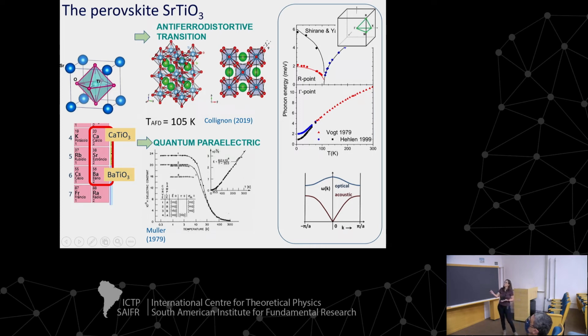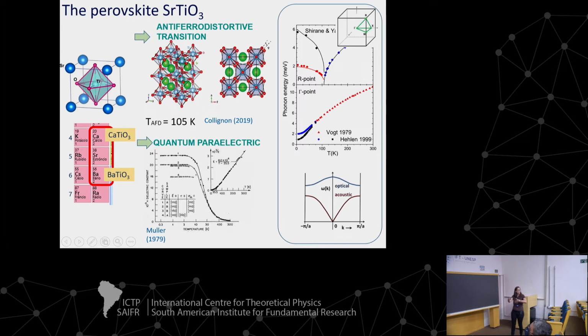Just to remind, this is also from the textbook, what we expect can contribute to transport are phonons that are acoustic, not the optic ones. So when we are in the presence of soft modes, which are basically optical modes that soften and show a dependence on temperature, it's like we have additional channels that allow scattering that preserves momentum. And this is the way that, from an observational point of view, we have interpreted our evidence.